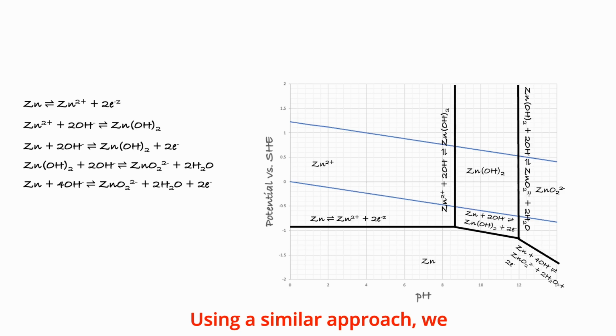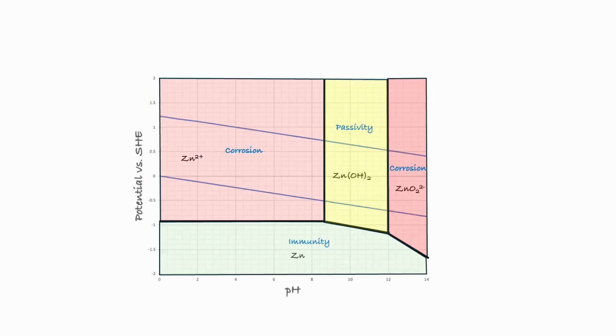Using a similar approach, we can also construct the Pourbaix diagram for metals, such as zinc. By writing down all chemical and electrochemical equilibria involving zinc, we generate the various lines on a pH potential diagram, and the lines separate different regions of stability for various zinc species. In this diagram, we find regions where zinc metal, zinc 2+ ions, zincate ions, and zinc hydroxide are stable. Hence, under conditions of pH and potential below these lines, reduction of zinc ions in the solution to form metallic zinc is the thermodynamically favored reaction.